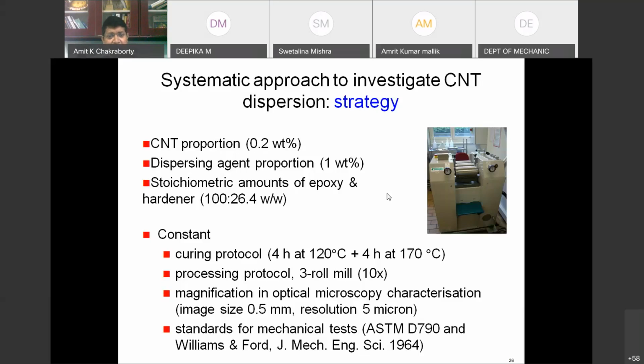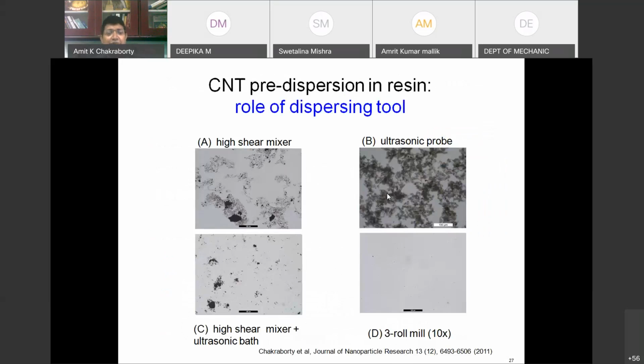So then I thought, okay, let me do a very bottom-up approach. I study from the bottom. We used a very small content of CNT, 0.2%, so that the CNTs themselves are not in contact with each other, and then we dispersed them in an epoxy resin. Then we simply used microscopic methods, that is optical microscopy, to study their dispersion properties. And here are the dispersion studies. This work was published in 2011, and this work is highly cited.